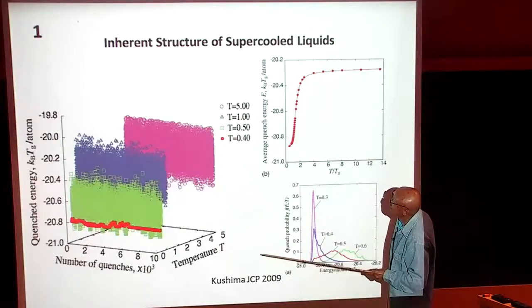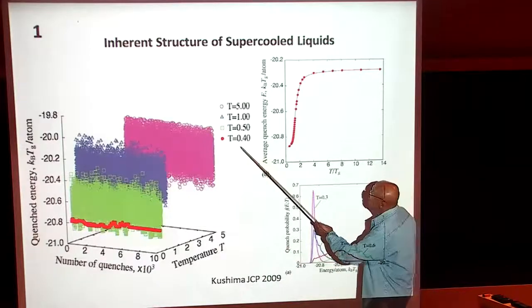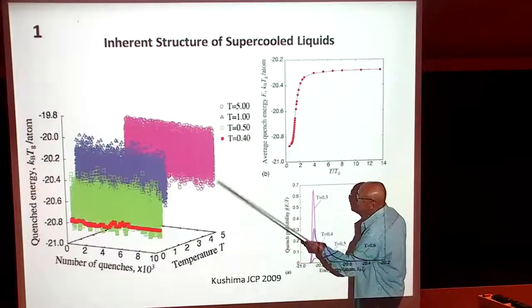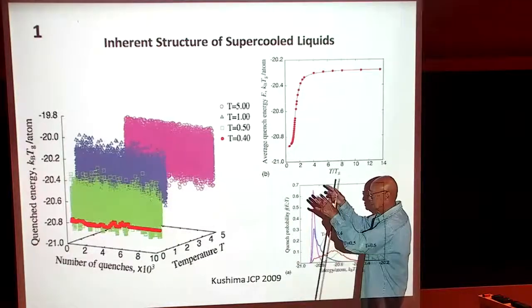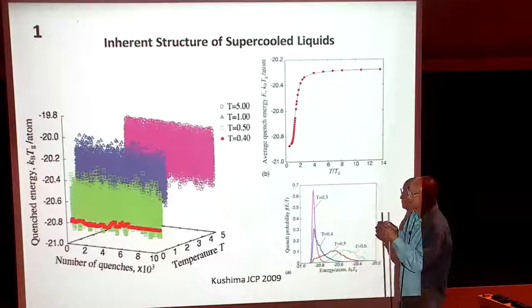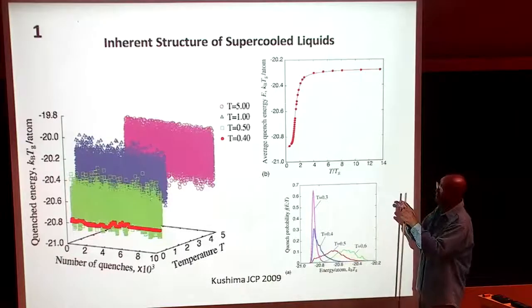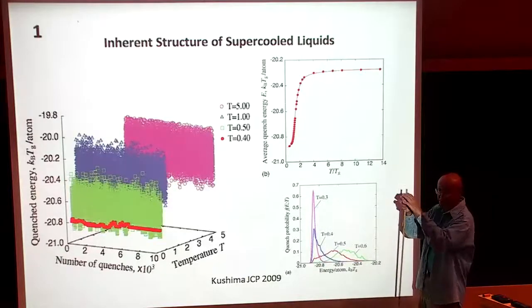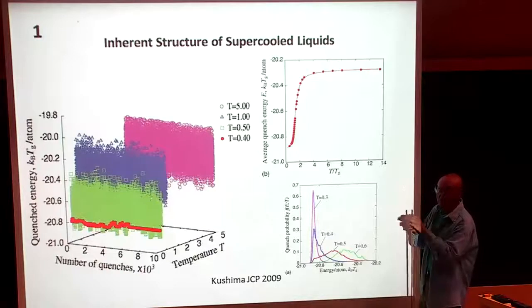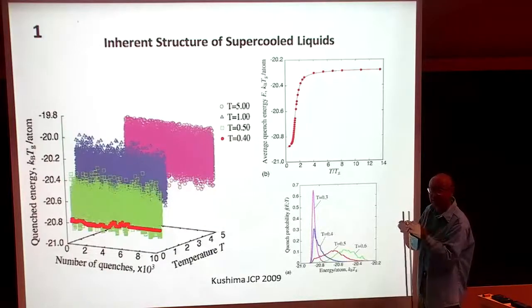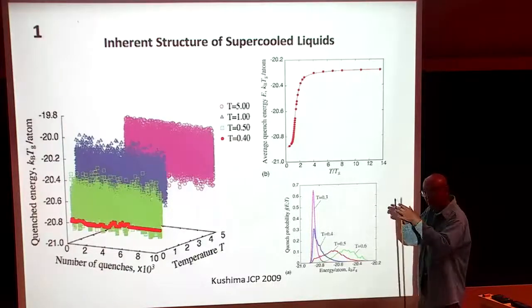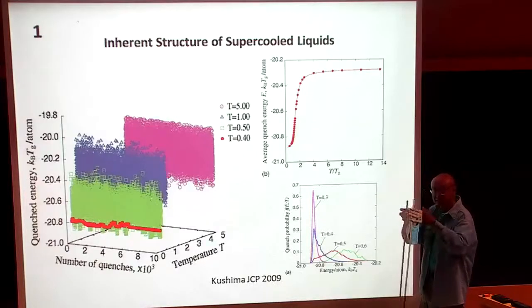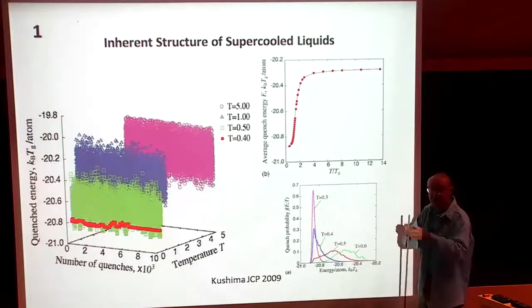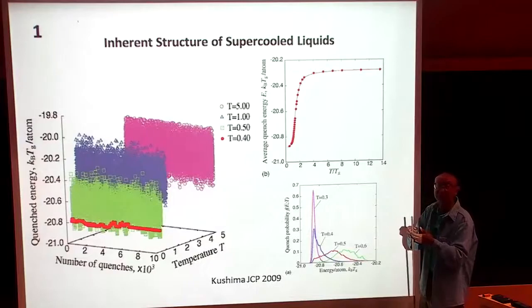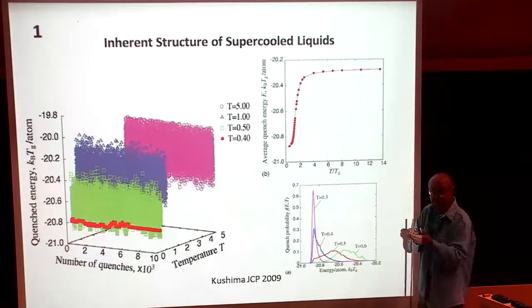Oh yeah, here it is. So if you take your MD simulation at various temperatures, equilibrate the system, run it as long as you can, so you're sure you have a liquid. Then during the simulation, at various instances of the simulation, you simply drop. You do a steepest descent quench. You just do energy minimization.